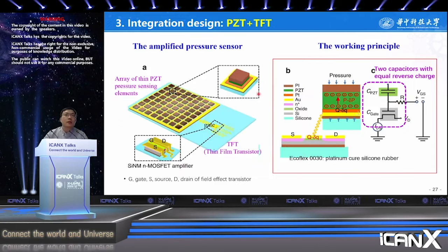A schematic illustration of a thin, comfortable piezoelectric pressure sensor. These devices include a square area of piezoelectric thin film transducer based on PZT, the green one. Each PZT film is encapsulated above and below with PI film, the brown one. All these pads are interconnected by a gold layer. They're supported by a silicon substrate, the blue one.